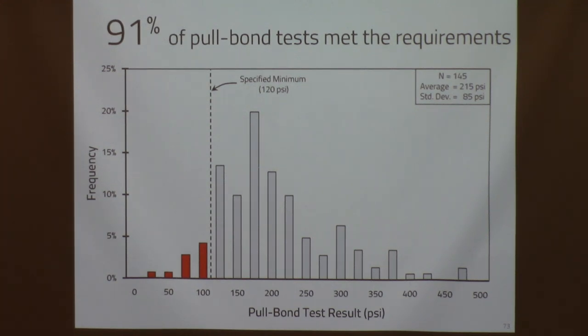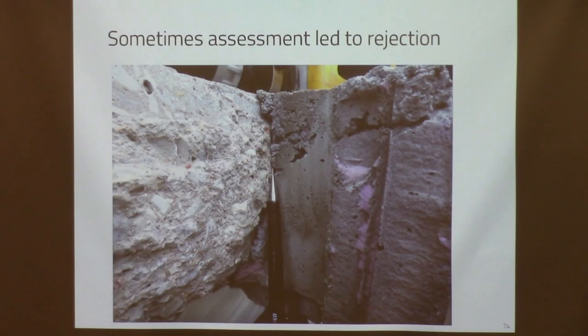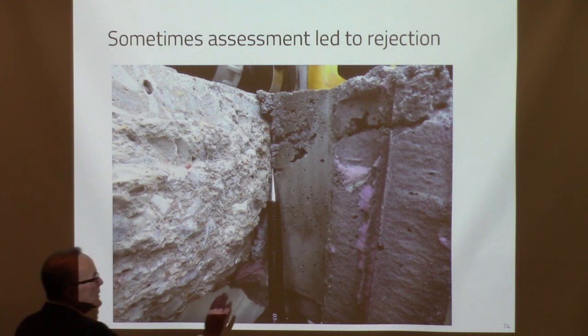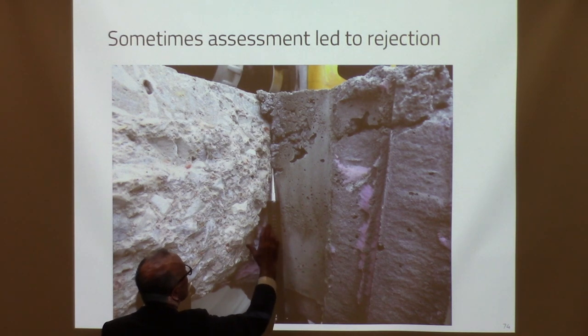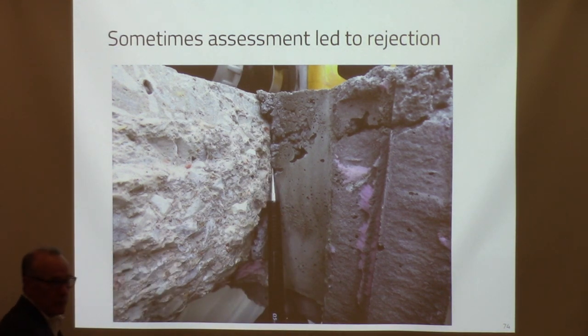Well, we do a little bit of investigation to see if we could figure out, was it the testing, was it something else? And in most cases, when that happened, we'd go up there. You can see here an edge of the new concrete, repair concrete, and then you look up along that edge, you can see really not good consolidation across that surface. It was poorly consolidated. You didn't get a good marrying of the new concrete with the old concrete. We've got poor bond strength.